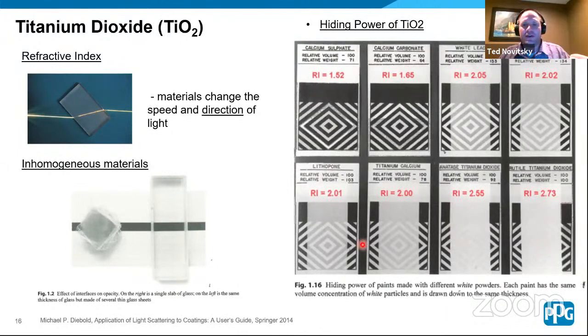And so what this graph is showing is 8 different paints with different amounts of inorganic materials in here. So we have calcium carbonate, we have zinc oxide, we have titanium calcium, and they have the same particle size, and they have the same amounts of materials in there. And you see that the titanium dioxide is very white. It has a really good hiding compared to the same amount of calcium carbonate, which you could barely even tell that it's there.